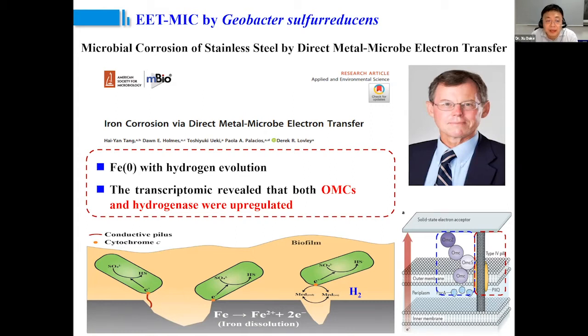First of all, the zero-valent iron they used can be coupled with cathodic hydrogen evolution. And the second concern is based on their transcriptome data: both the hydrogenase and the outer membrane cytochrome C are upregulated. So we cannot confirm the role of these outer membrane cytochromes. Are they really responsible for MIC?